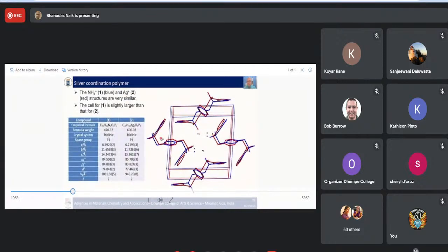The difference, as I showed you, is very small between the two compounds. You can see that the backbones of the ligands are almost superimposed, and the silver and the ammonium cations are in the center here. The ammonium compound, which has hydrogen bonding, is slightly larger, because with hydrogen bonding you push out the oxygen a little bit. You can see the blue here is compound 1, the compound with ammonia, and you can see that the oxygen is a little bit further out. So the ammonium is slightly larger, and you have a very slightly larger volume of the cell. It's 1081 versus 945 cubic angstroms.